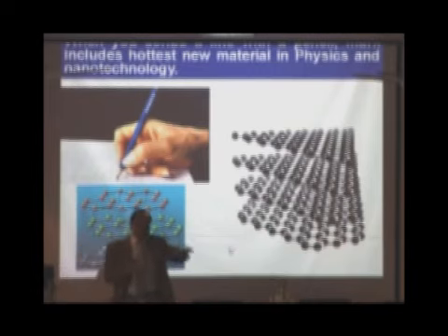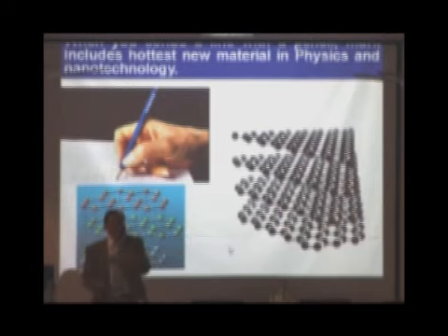The substitute for the ITO layer, the graphene layer, is it now commercially available? And what would be the stability? This is not my work. There are beautiful papers which have shown this highly conducting and transparent layer. They have achieved it, which we have also achieved. Once you make chemically produced graphene, you can spread it on any place you want. People have grown this graphene layer on 6-inch glass. Resistivity is low, but transmission is still 85%. If 85% is acceptable for some application, it is fine. But if you want 90% or 95%, then you will have to work on it.